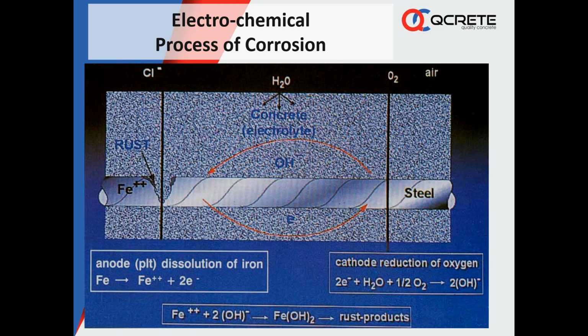You can see here, as soon as the moisture along with the chlorides touches a particular steel ring, that portion will act as anode, and the rest of the steel will act as cathode. The concrete will act like an electrolyte. Ferrous gets converted into ferrous oxide and hydroxide, and slowly the rusting takes place. And you can see the size of steel increases 6 to 6.5 times, due to which the cover portion, which is the weakest portion, comes down.